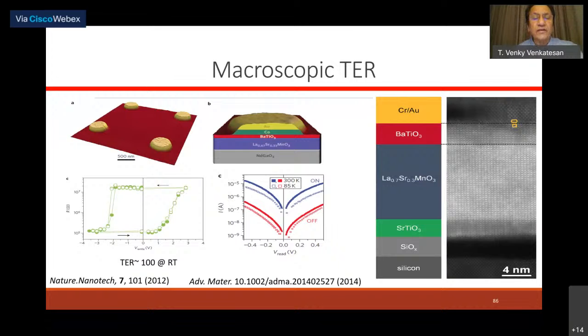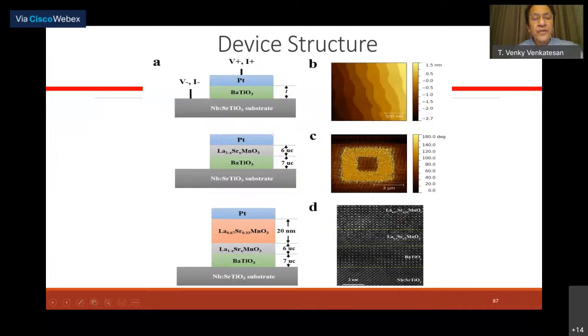So we started studying this very systematically. Here we take a niobium-doped strontium titanate substrate, which is a conducting substrate. We epitaxially grow a barium titanate layer on top of it. Now, imagine all of these are atomically controlled processes. That means every layer is essentially counted in terms of unit cells. So this barium titanate is n number of unit cells, and we know exactly what that is. And then on top of the barium titanate, we put the platinum electrode. So this is the simplest tunnel junction you can make.